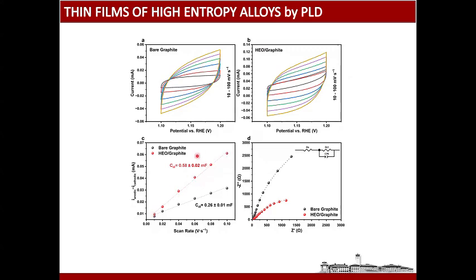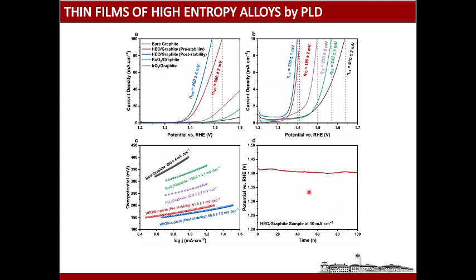The electrochemical surface areas for the high entropy films are high compared to the bare graphite electrode surface, and also the surface resistance is low according to this impedance analysis. So the high entropy oxide, I will call it high entropy oxide because now it's oxide, like nano-oxide and high entropy oxide nanoparticles. The overpotential is around 300 millivolts. It is much lower than the previous example.